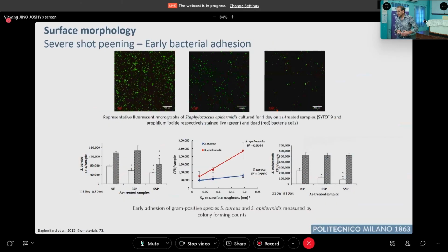Okay. And then we talk about cells. If we talk about bacterial adhesion, what can we see? Also in this case, the effect of the treatment changes if we consider different times. We see after 1 day and 2 days that also in this case, the effect of the treatment tends to disappear with increasing time. But for bacterial adhesion, having a reduced bacterial adhesion rate is even more important to avoid infection. And this is obtained by using CSP or SSP. This is also an encouraging and interesting result for possible application also for this kind of component.